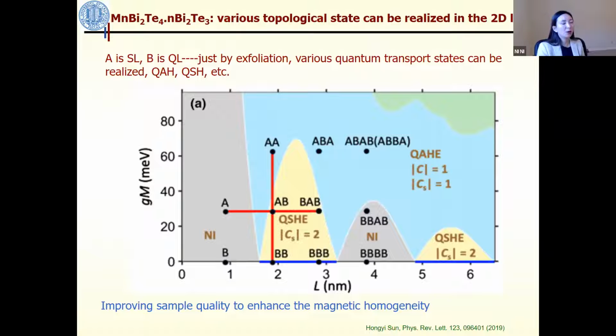Okay, so our last comment here for this MBT family, because I want to emphasize, is that this family of compounds are natural heterostructures. Which means when you do exfoliation, you will be able to get the heterostructure just by exfoliation, rather than doing MBE growth, where you grow one layer and then grow the other layer. No, we have this bulk material, and just by exfoliation, you will be able to have a different combination of the QL and SL layer here.